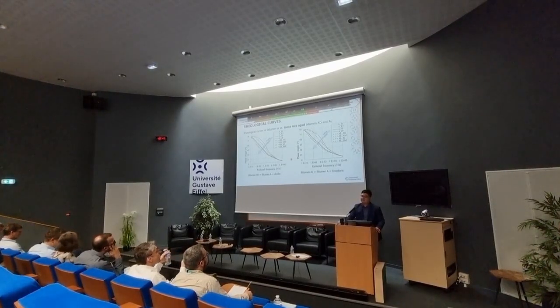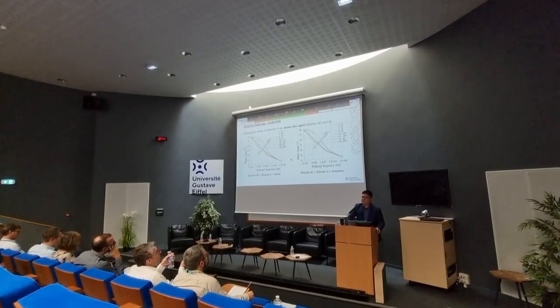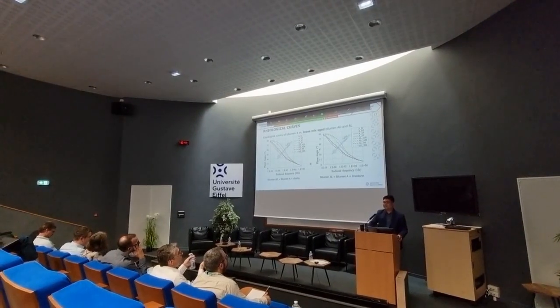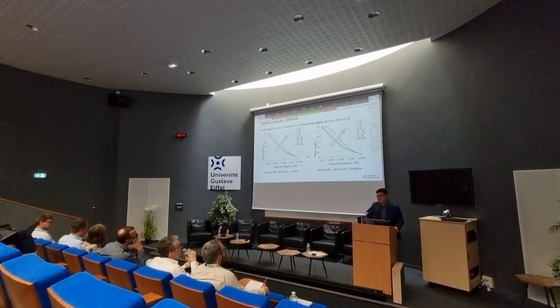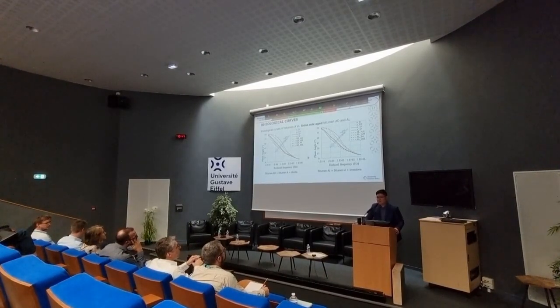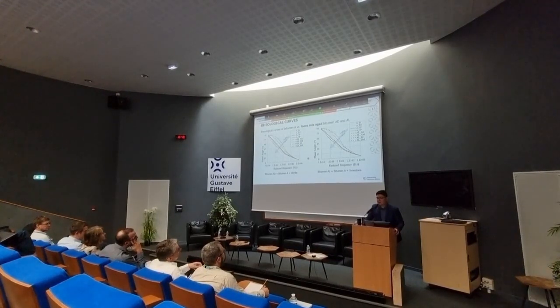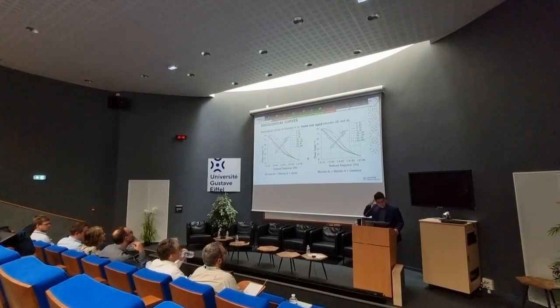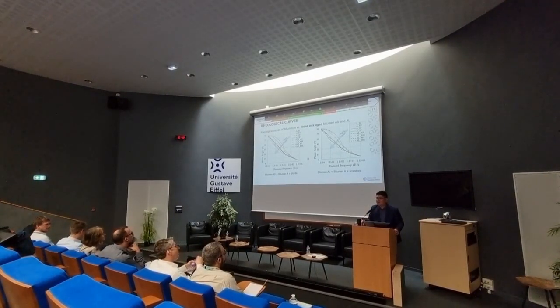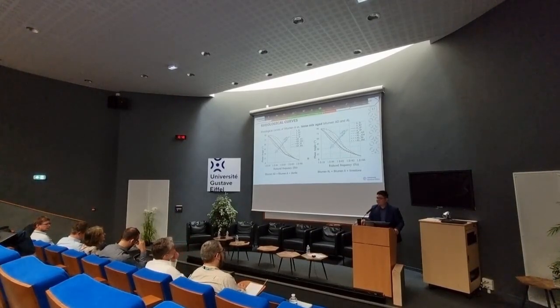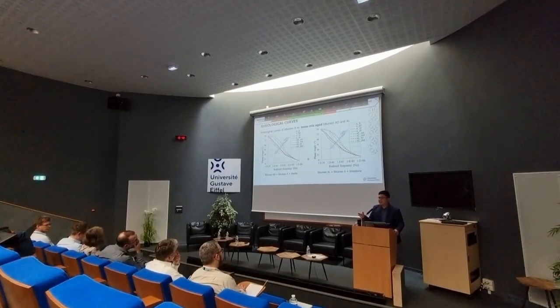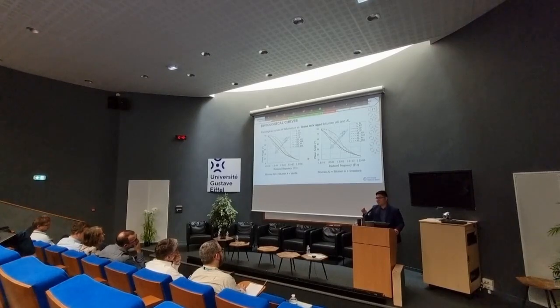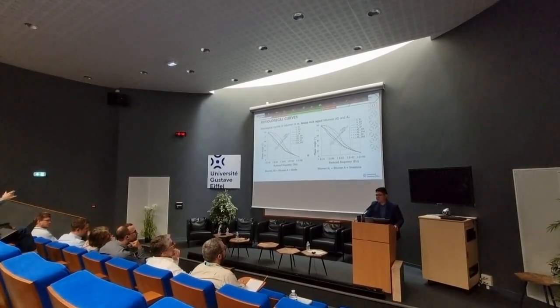Is it the life duration of the bitumen? I don't think it's sufficient, because obviously temperature would play a role. I think it's very complicated to find direct correlations between bitumen performance and, for example, in the end of chapter four, I tried to compare bitumen recovered from mixed aged and field aged samples with the four aging levels of bitumen A, which was fresh, for example, T, 1 PAV, 2 PAV. And what was funny was that depending on the parameter used, we could have different classifications.